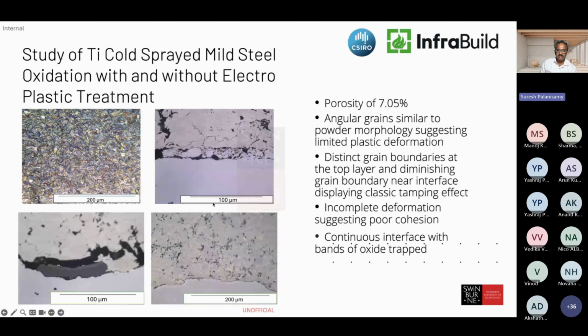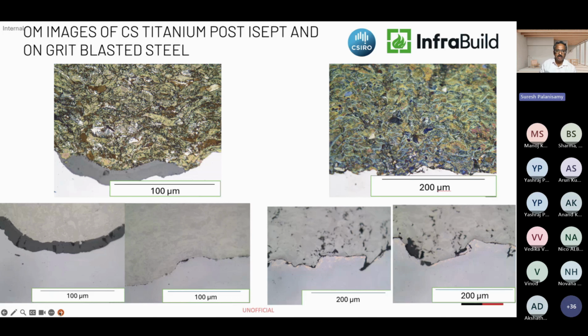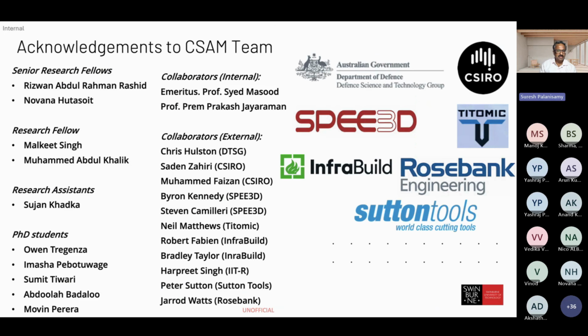So finally, in these last few slides, another application to look at is using low-cost powders or recycled powders in this particular case to mitigate corrosion. Titanium powder particles are used on a steel or mild steel substrate because this is for the building industry sector. To avoid corrosion, we use titanium to coat a grit-blasted steel, as you can see, and different properties can be achieved. As most people might know, titanium is far better in a corrosive environment. That's why we are trying this with the low-cost powder also, with different post-heat treatment conditions in this particular case. So consider the time factor.